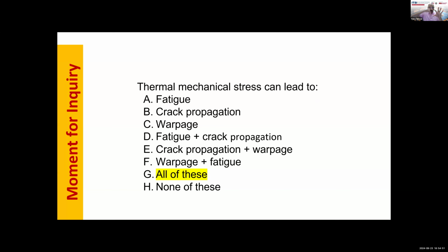Thermomechanical stress can lead to fatigue. So when we heat it up, we stretch, relax, stretch, relax. You heat up, you spread or extend the length, dimension. Cool it down, you shrink again, heat it up. So that fatigue, that's some thermomechanical stress. Crack propagation. Now, if you have a crack, ceramics just inherently have surface flaws. That's just part of ceramics. But when you start cycling and you heat, and then you go too high, you create this thermal stress. And at the tip of the crack, you get a concentrator where the stress is really intensified. You get crack propagation. That leads to catastrophic failure.